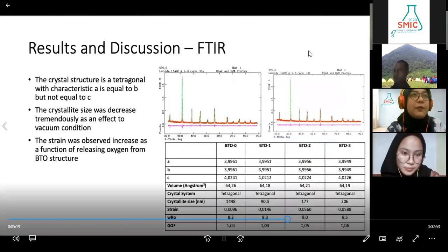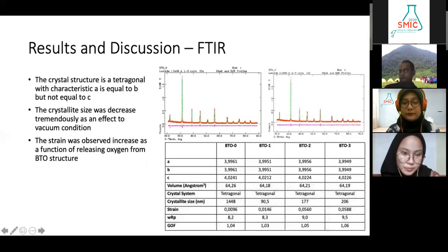Then for XRD, the crystal structure is tetragonal, with the characteristic that parameter A is equal to B but not equal to C. Then the crystallite size decreased tremendously as an effect of the vacuum condition, as we see from the value of 1448 nanometers, it decreased to 90.5 nanometers at the first sample. Then for the next sample, it increased as crystal growth started. Then the strain was observed to increase as a function of releasing oxygen from the BTO structure.